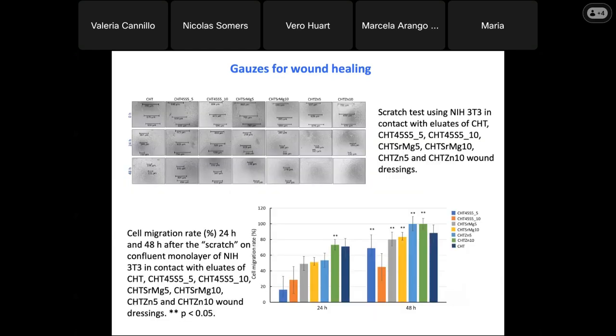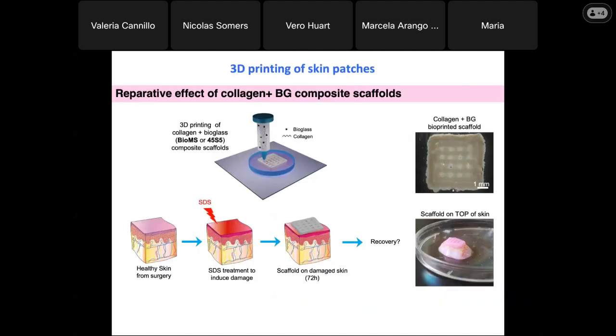In this case, the gauzes were tested in vitro using a very simple test, which is the scratch test, in which you produce a scratch and then you see when the scratch is closed. And in the graph, you can see the cell migration rate after 24 hours and 48 hours. And so as you can see, the gauzes produced with the novel bioactive glasses gave very promising results. Then we did something to regenerate difficult wounds, such as those of people with diabetes.